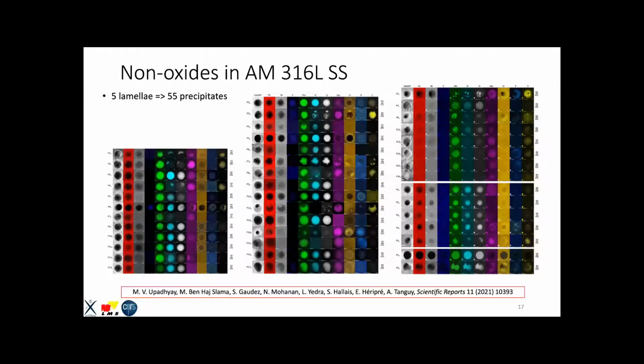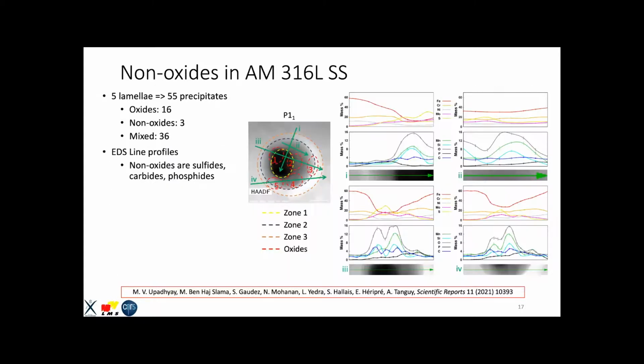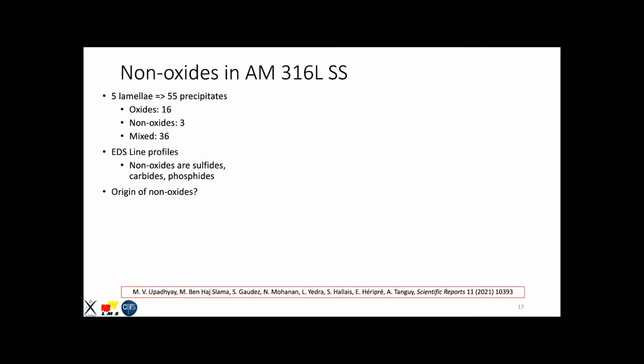We characterized all of them with EDX and found that there were 16 oxides, 3 non-oxides, and 36 of them were mixed oxide and non-oxide precipitates. We did EDS line profile analysis on every one of them. In some cases, we had to do more than one line profile analysis. For instance, this one was quite complex, so we did it a lot. We found that these non-oxides were sulfides, carbides, and phosphides, and in some cases intermetallics.